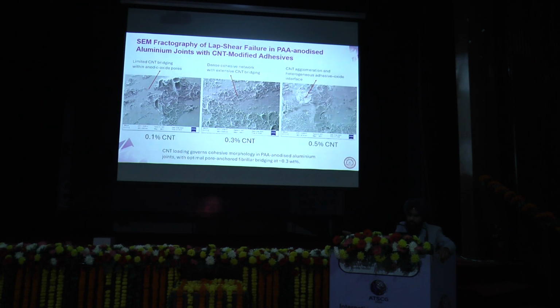So these are some micrographs showing the lap shear fractures for PAA anodized samples with CNT modified adhesives. So in the first case you can see with 0.1% volume percent of CNT, bridging is observed within anodic oxide pores, which is indicating insufficient network formation of the pores. At 0.3% you can see dense cohesive morphology with extensive CNT bridging, and at 0.5% volume you can see the agglomeration occurs, creating a heterogeneous adhesive oxide interface near the lap shear joints.